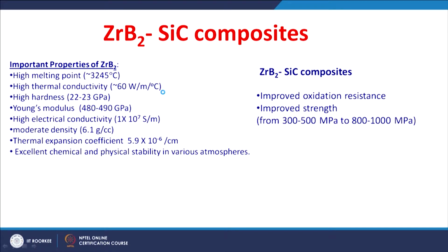So, in the family of the ultra high temperature ceramics, zirconium diboride based ceramics are attractive because of their important properties. For example, very high melting point of more than 3200 Celsius, high thermal conductivity of around 60 watt per meter per Celsius, and very high hardness. So, that may lead to superior wear resistance. Young's modulus is very high, around 500 gigapascal, with good conductivity and moderate density. This moderate density is helpful for using this material for structural applications. And so, excellent chemical and physical stability in various atmospheres makes them candidate materials for high temperature applications.